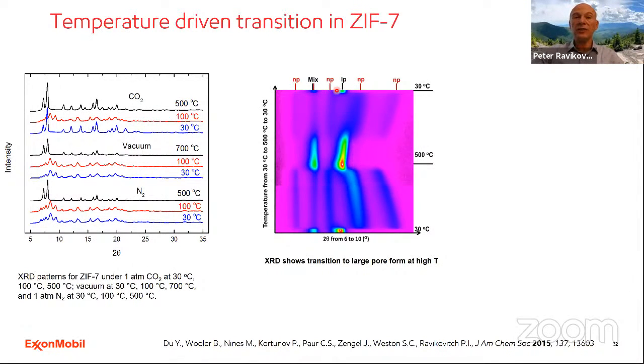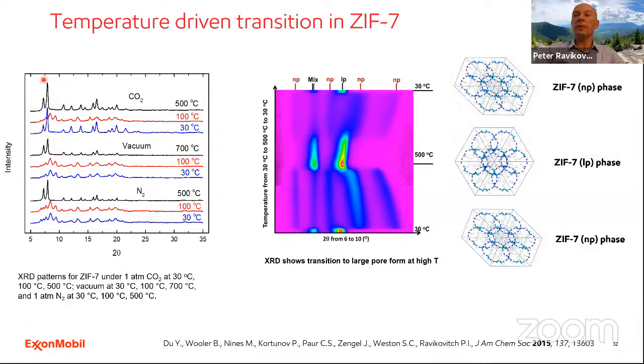And a similar transition happens in the presence of gases. So for CO2, the material at 30 degrees C is already in the large pore phase because CO2 is adsorbed. Then you start heating it up, CO2 desorbs and the material reverts back to the narrow pore phase, but then upon further heating, it reverses back to the large pore phase. So it's a reversible transition. How can we rationalize this transition?